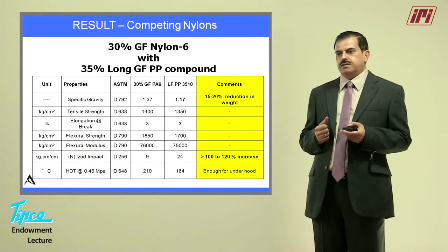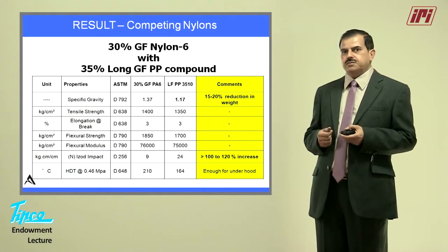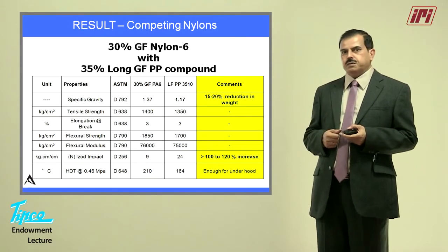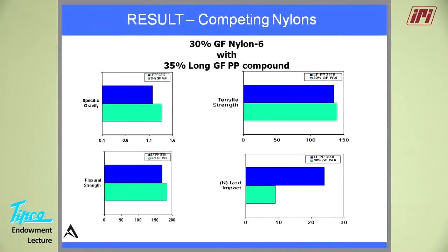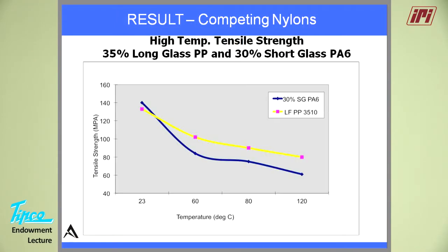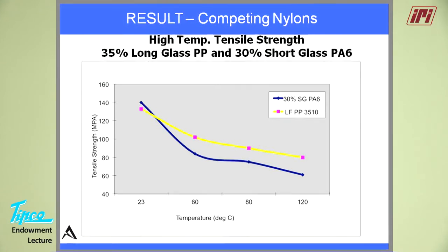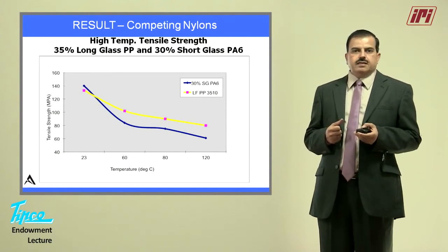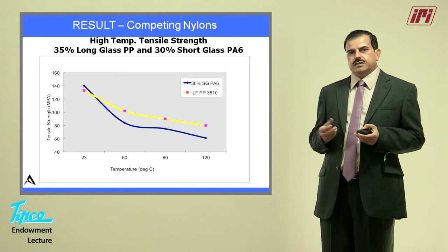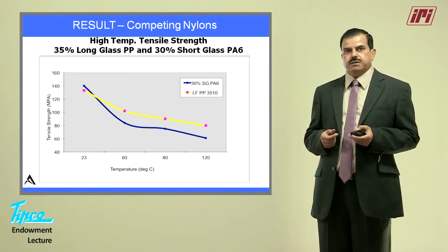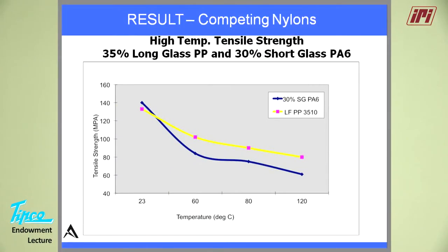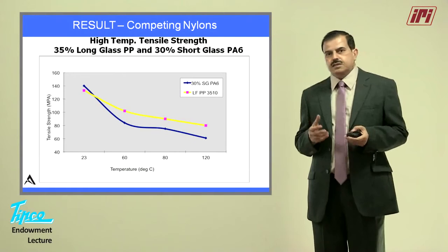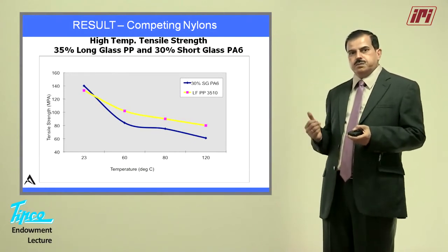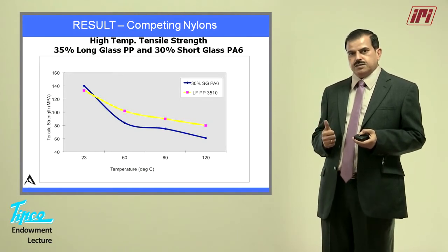By doing this comparison, we have tried to replace many nylon 6 30% glass filled applications with 35% long glass fiber PP compound. This is a graphical presentation of the same properties. Many times it was thought that probably the long glass fiber PPs, because PP is the binding resin for the glass, probably will not behave in underhood applications where the temperatures are slightly high. But as you can see, the yellow line, up to 120 degrees centigrade, the drop of tensile property of long glass fiber is lesser as compared to 30% nylon 6. So if you test the tensile strength at 120 degrees centigrade, long glass fiber PP gives a better property than nylon 6 30% glass filled.